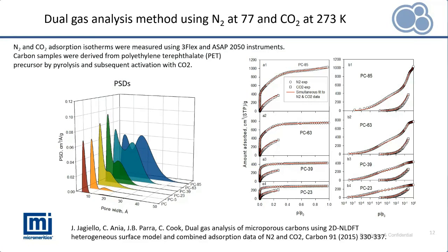For the analysis of microporous carbons, we developed a dual gas analysis method in which we simultaneously fit the 2D NLDFT kernels for CO2 and nitrogen to the corresponding experimental isotherms, and in this way we obtain the full pore size distribution for the analyzed carbon. An example of such analysis is presented by this slide.